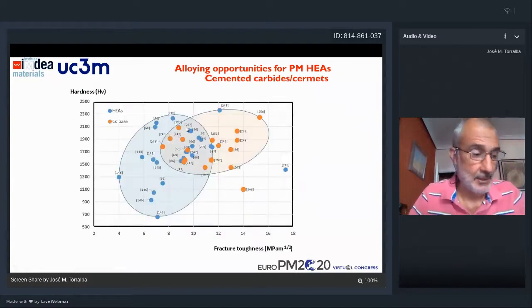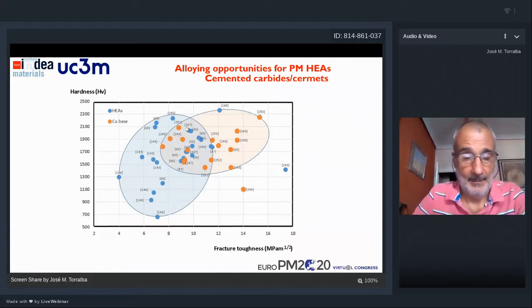Another possibility, of course, is to develop cemented carbides in order to replace cobalt as binder in the conventional hard metal. Here we have, in this color, cemented carbides with cobalt, conventional cemented carbides, and here we have high entropy alloys used as binder, replacing the cobalt. Here we can see that we have an interesting area in which we can compete with the conventional cemented carbides. This is a topic which is under development, so we can really develop these possibilities much more in the future. We have plotted here just materials produced with similar processing conditions. So these conventional cemented carbides have been compared with those manufactured with HEAs, the high entropy alloys.